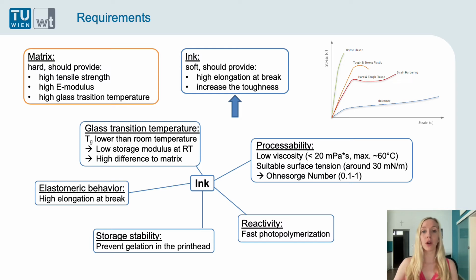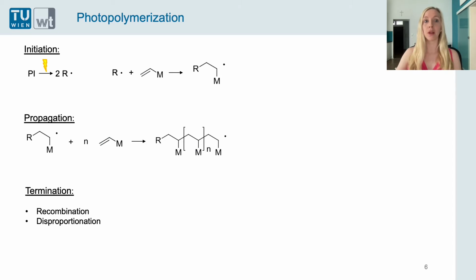Also the reactivity is important, so we want a fast photopolymerization because the ink is only irradiated for a few seconds. So if you are not so familiar with photopolymerization, here is a short introduction. First you have an initiation step where a photoinitiator is cleaved by the irradiation of light and two radicals are formed. Then these radicals can add to the double bond of a monomer, and a new radical is formed on the monomer molecule. Then the second step is the propagation, where the newly formed radical can add again to a double bond of a monomer, and in this way a chain is formed.